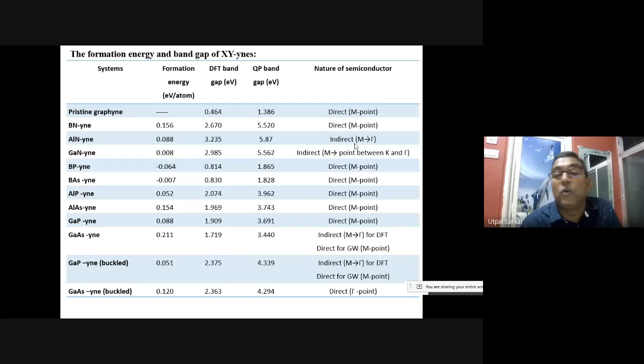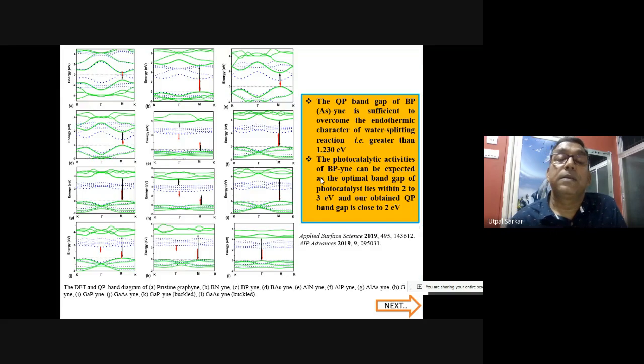So what is interesting here is that the band gap in most of the systems is a direct band gap and located at the M point. However, some indirect band gaps are also available. Okay, so even if you consider two different formalisms, one is DFT, another is GW, then you see that the indirect band gap for DFT calculations is in between M and gamma points. However, using GW calculations, we are getting a direct band gap at the M point only. And these are the cases for gallium arsenide and gallium phosphide. Okay, so very interesting.